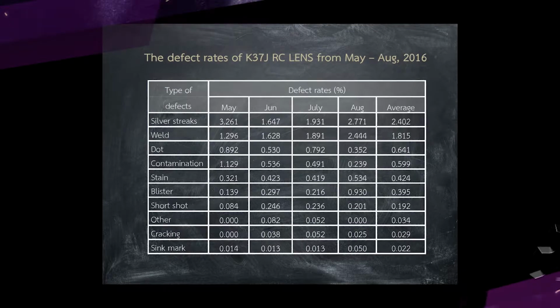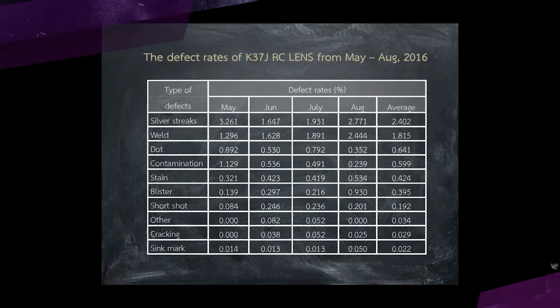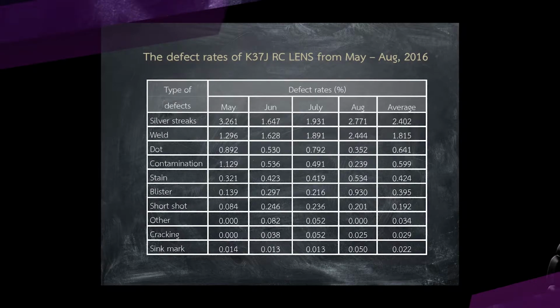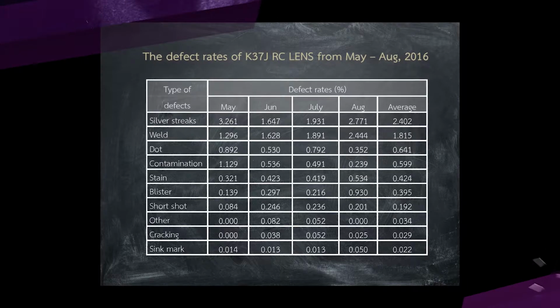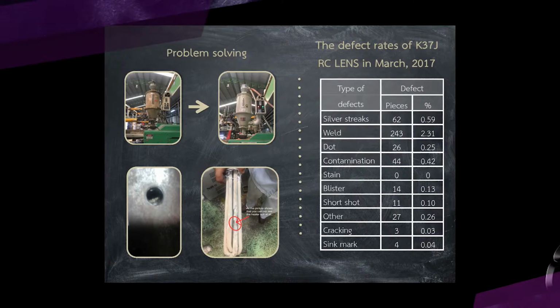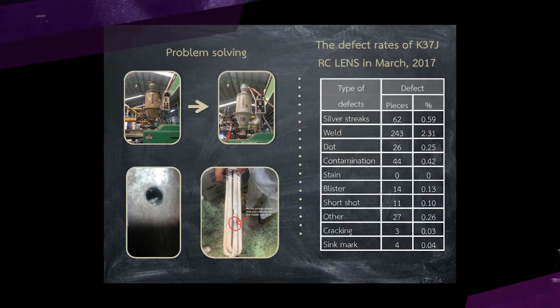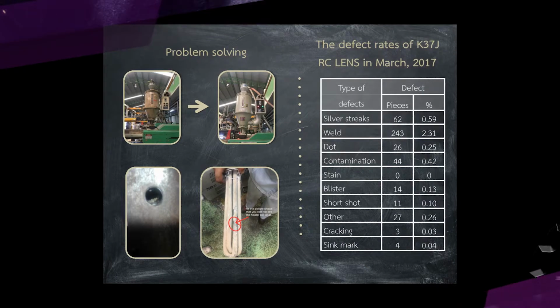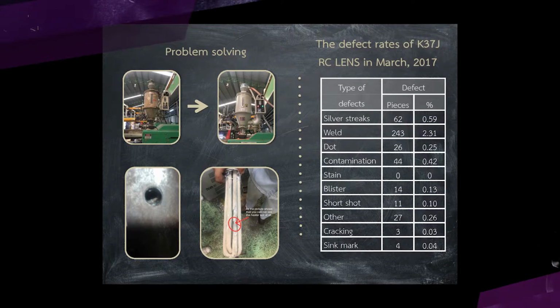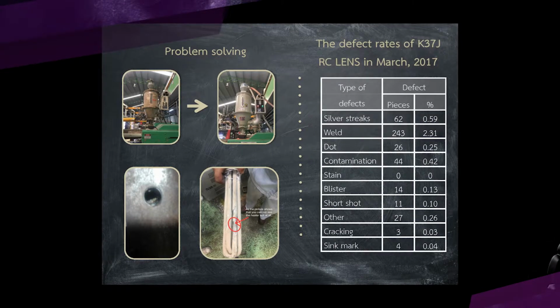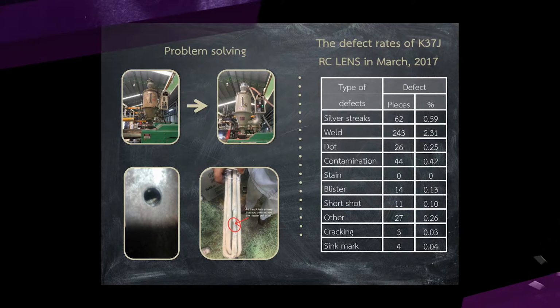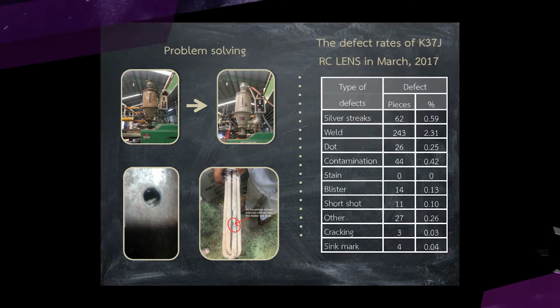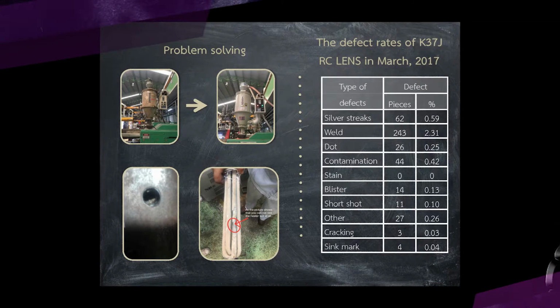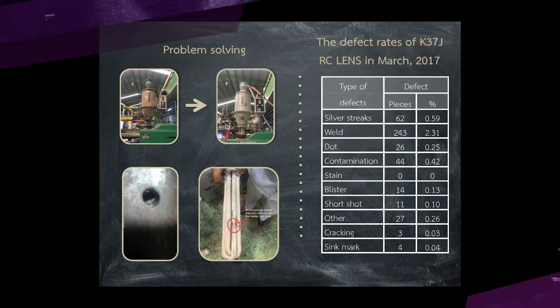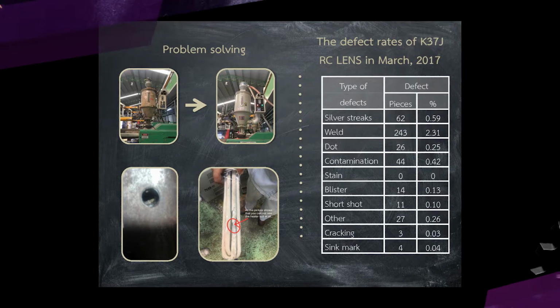We then used cause and effect analysis to analyze the potential causes of the defects, and it was found that silver streaks occur from the hopper dryer. The problem of silver streaks occurs from the edge of the hopper dryer, which is old, and it allows moisture to access the dryer, and the filter inside is also broken, so the preheating process could not be done properly. So we decided to change the hopper dryer from the old one to a new one.